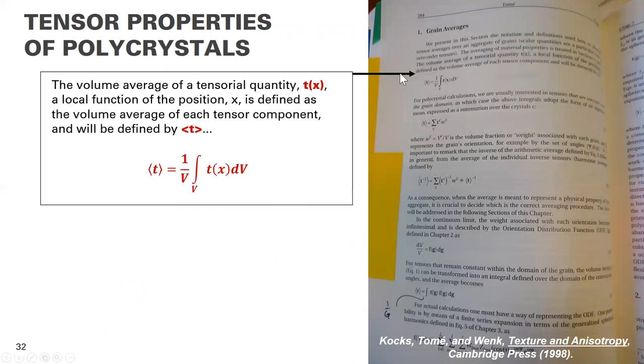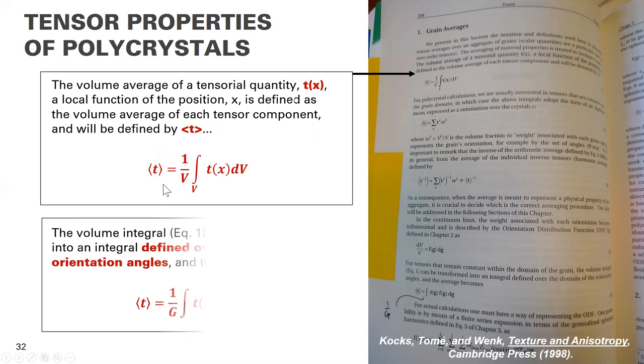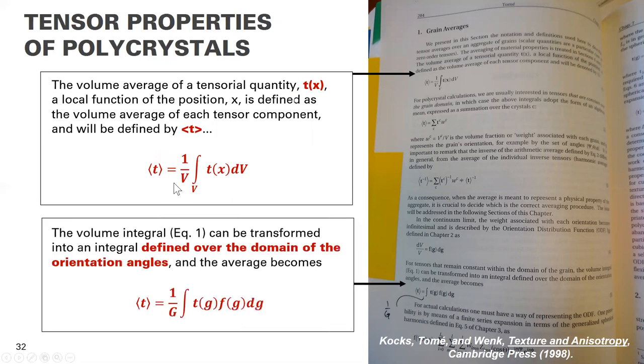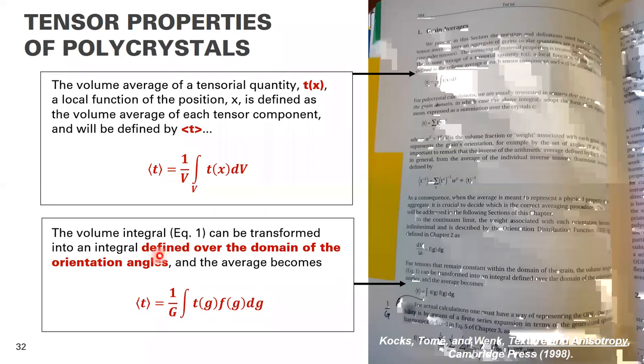So back to textbooks. How do you connect microscopics with macroscopics? Well, in this texture book that I mentioned before, there's a very interesting chapter on grain averaging. And I just pulled out a couple representative equations from this. The first one in this chapter shows you the volume average of a tensorial quantity T of X as a function of position X in the sample. Traversing through the sample, you can imagine that if you average positionally, you could get the average effect in a polycrystalline aggregate. But texture researchers extend this to doing an integral over orientation space. And so here, the volume integral shown above can be transformed into an integral defined over the domain of the orientation angles, okay? Which, as we said before, is this lowercase g. So we're integrating over all of the orientations.